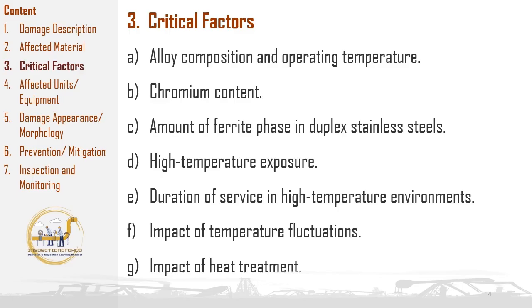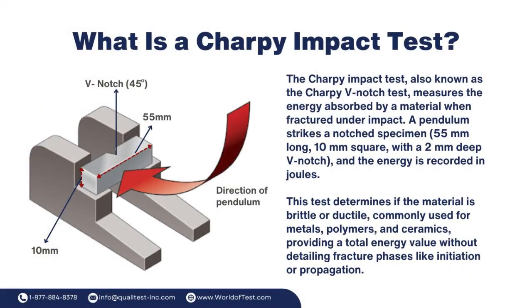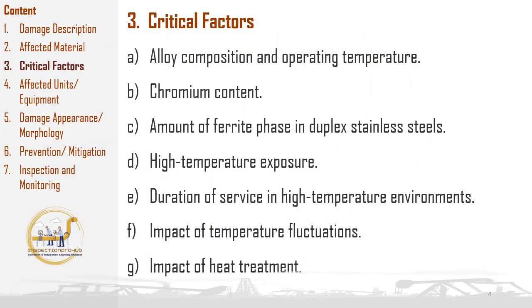On 300 series stainless steel weld metals, although embrittlement has not been extensively observed across all, Charpy impact tests on Type 308 and Type 347H weld metals aged at around 850 to 885 degrees Fahrenheit have shown signs of embrittlement, with some samples showing impact values below 15 foot-pounds at ambient temperatures. Despite these findings, embrittlement is generally not a major concern in typical refining applications where these materials are commonly used.